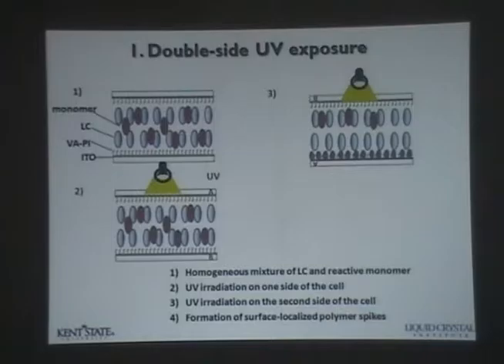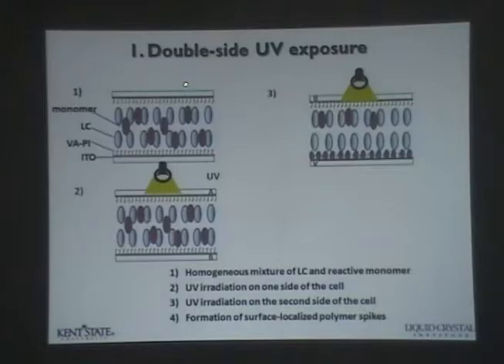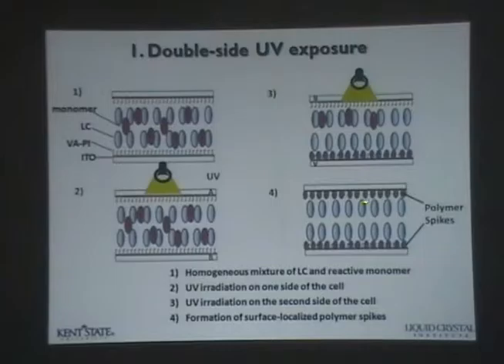Once you spin-coat a certain thickness of this polyimide film, automatically the side chains of lower surface energy like to stick out into the air — that's how you get automatic vertical alignment. You can also use lecithin in the lab. You dissolve the lecithin in hexane, dip your glass into it, dry the organic solvent, put it in the oven to make sure all the solvent has been removed. In the cell structure, top and bottom substrates have this kind of vertical alignment polyimide. You then fill the liquid crystal with some percentage of monomer.